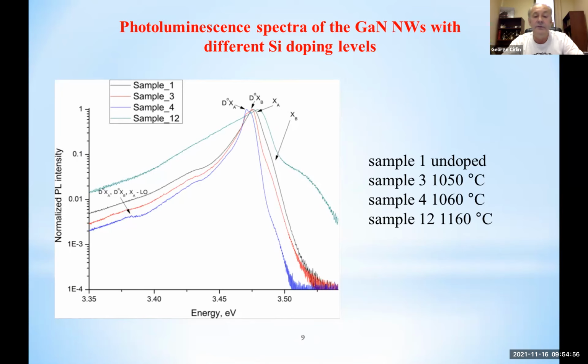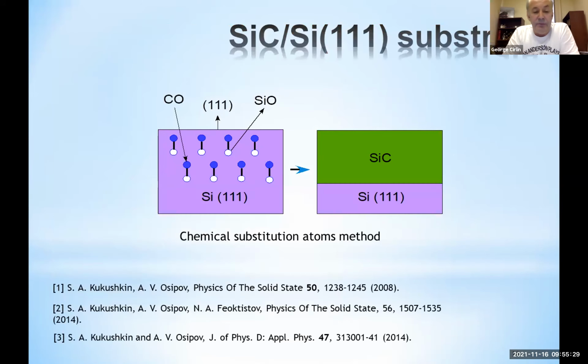And in some extreme cases, when the temperature of the silicon source is quite high, we may observe the emission of the exciton which is beyond the band gap of gallium nitride. And it was explained by the so-called Moss-Burstein effect, which we can discuss a little bit later.